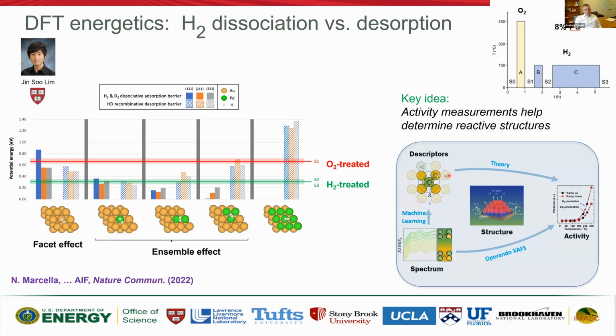And so by doing this, I hope I convinced you that we can really do this analysis in the framework shown here, where instead of knowing the structure by directly measuring it, which sometimes is not possible, we go around it and measure the spectrum indirectly, using machine learning to decipher it, and use the information as the input for theory that will model the experimental activity. And that will close the loop, and we will understand all we want to know about reaction mechanisms.